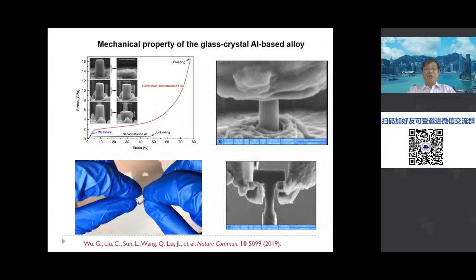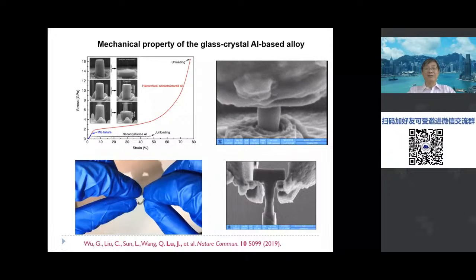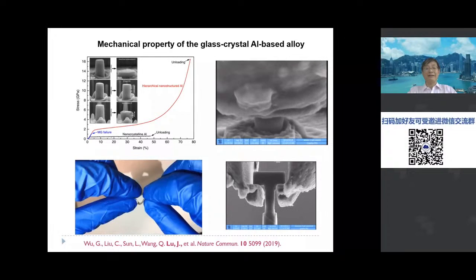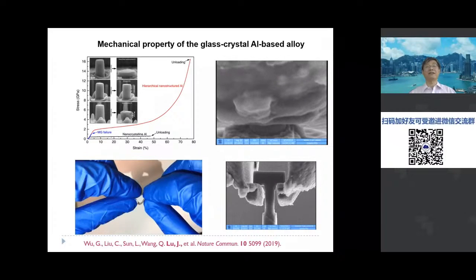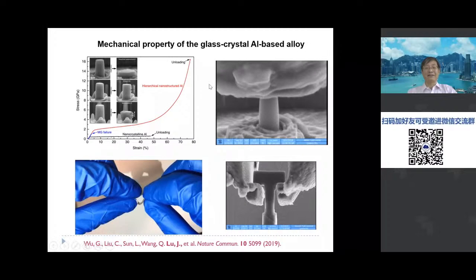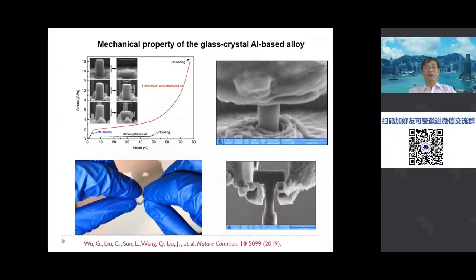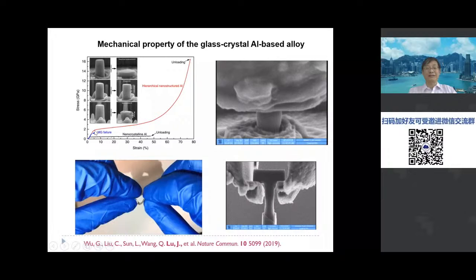When we load the material, if the grain size is slightly larger than 10 nanometer, we will have a structure embedded in the metallic glass that can generate dislocations inside the structure, plenty of dislocations because the grain size is very small. And these dislocations can accommodate the whole structure to enhance the deformation capacity. So we can tailor-make this dual phase structure depending on what property we want. If we want just super elastic property, we can do it. If we want some plastic deformation property, we can also tailor-make it.